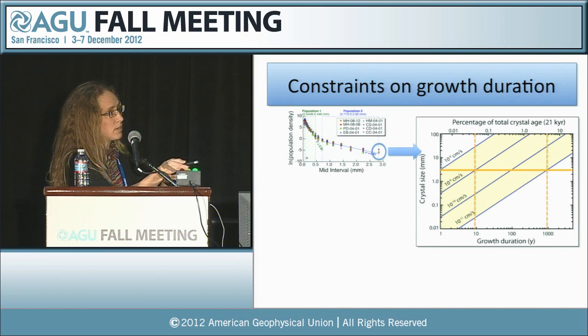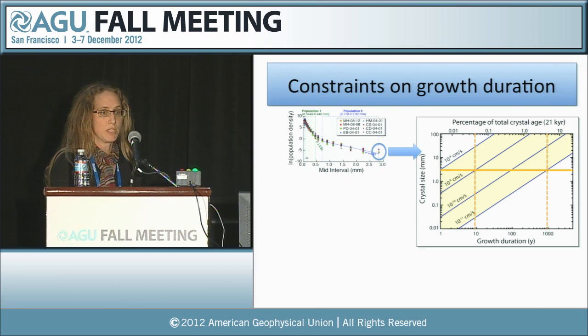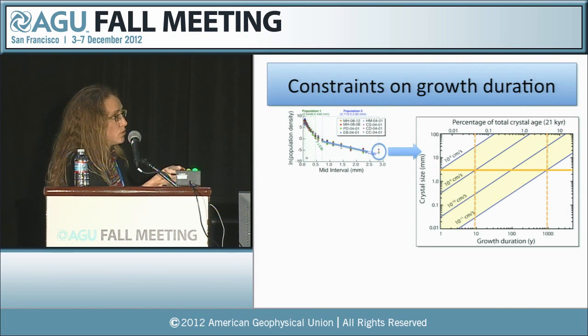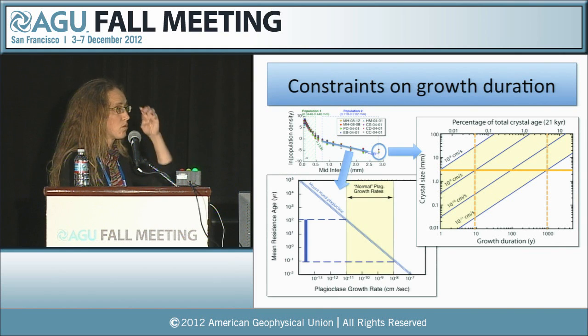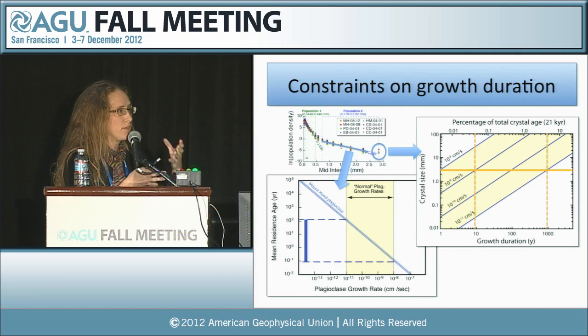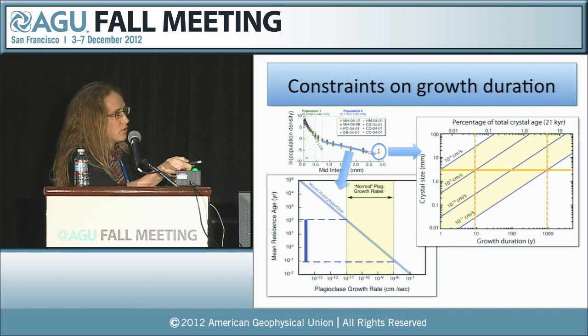But when you compare that to the total minimum crystal age of 21,000 years, we're still getting something that's a fraction of a percent up to only a few percent of the total time that these crystals existed, that they spent growing. We can also use the slope of the CSD to get another estimate of the time scale of crystal growth. There are various ways that you can interpret this slope, but if you assume a steady state open system, you get a mean residence age from that slope, which corresponds in this case to up to about a century, so a little bit shorter.